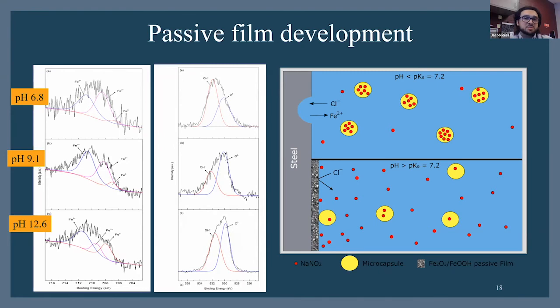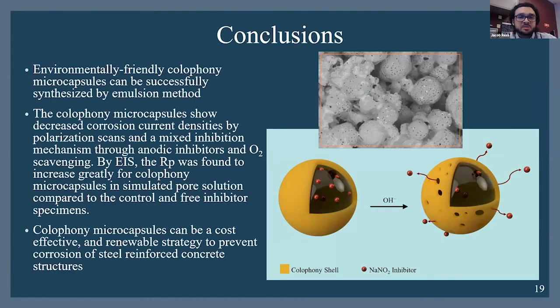And a schematic of the system shown here is just that at our lower pH values, some inhibitor is released, but we have evidence that it's a low amount, showing that the corrosion will still take place. However, in the alkaline solutions, we see the release of our corrosion inhibitors. This can be beneficial. And lastly, this was beneficial because during the concrete curing stage, these microcapsules will be able to withhold the corrosion inhibitor solutions. And then as the pH of the concrete mixture increases, we have a release of our corrosion inhibitors, which will effectively diminish the amount of any leaching and premature binding during the initial stages, and allow for the more effective use of our inhibitors and less loss.